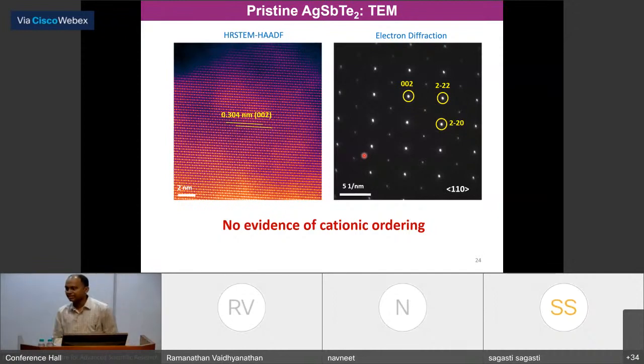Actually, yes. So this is the pristine sample, AgSbTe2. We have done careful HR-STEM high-angle imaging in a Titan microscope, collaborating with a collaborator from Shenzhen. And we have shown the intensity distribution is exactly similar, and electron diffraction shows only the fundamental spots due to the rock salt structure. We don't see any superstructure spots.